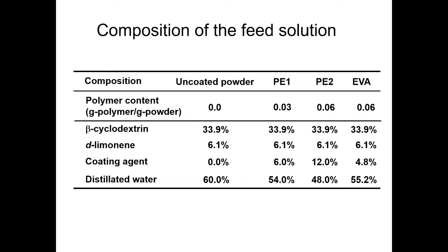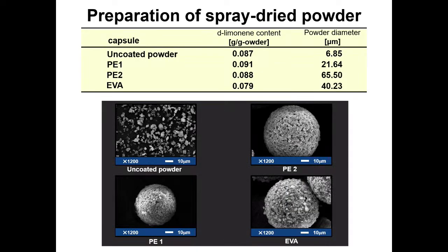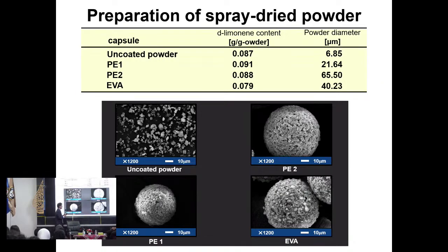So in this case, we use some kind of polymer coating agent with beta cyclodextrin, coated, and we make this kind of spray dried powder. This is a crystal of the beta cyclodextrin.